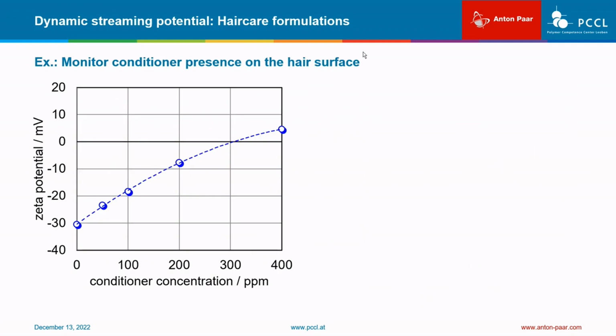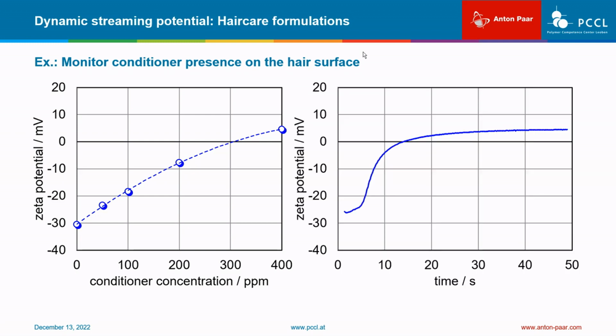The effectiveness of the conditioner may be optimized by recording the dependence of the Zeta potential of human hair on the concentration of the cationic component, such as a polyquaternium compound, or of the final conditioner formulation. In our hair washing cycle, we have used the final concentration of 400 ppm of this adsorption isotherm. The rate of adsorption and the time needed to achieve equilibration is finally communicated by dynamic streaming potential measurement following the addition of a certain concentration of the conditioner to the aqueous buffer solution.